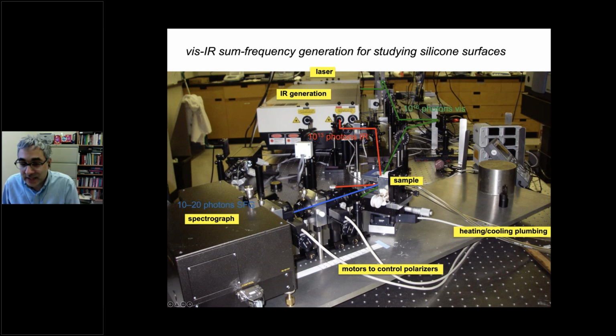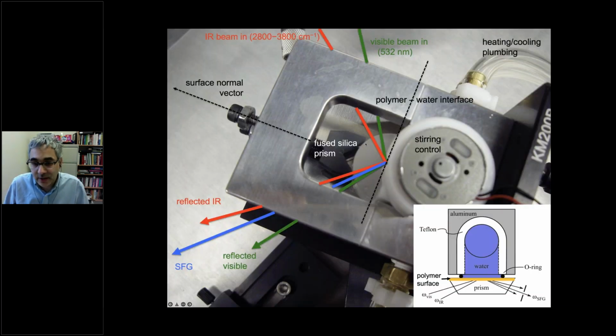So before I show you the data, I'm going to show you one more photo, and that is a photo looking straight down onto the sample so you can understand where the silicone rubber sits in this experiment. And if I were to take a drop-down view of the very middle of where the sample is, in this area right here, you can see it looks like this. So here's your incoming green laser, here's your incoming infrared laser, and in blue, these are just the few photons which are created just from that top nanometer of the surface.